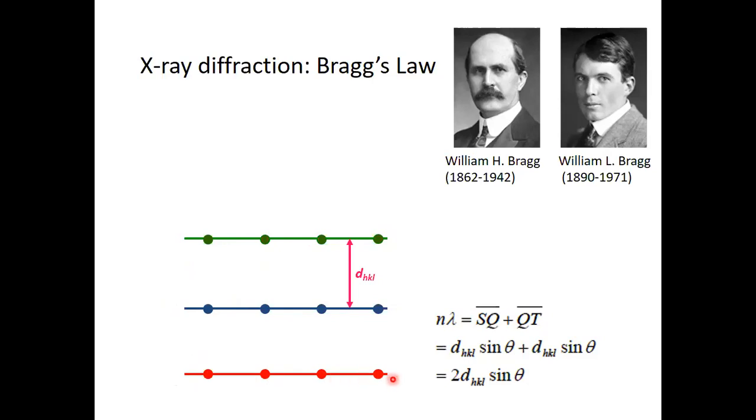So these lattice planes all obey the rules of periodicity. Therefore, they have an equal interplanar distance from each other, which is defined as d subscript HKL. So HKL, as we will learn in a little bit, are so-called Miller indices that define a family of crystal planes.